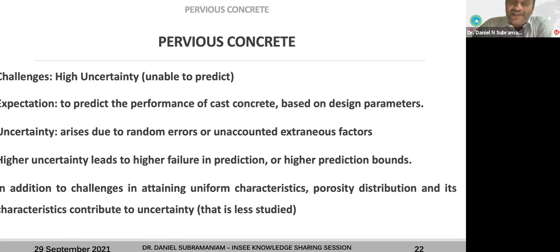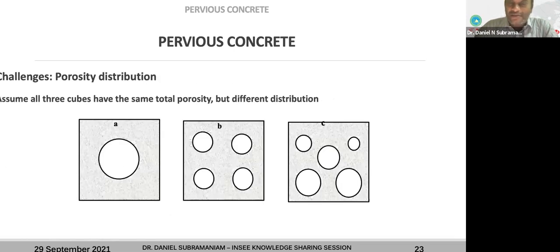So in addition to challenges in attaining uniform characteristics, porosity distribution and its characteristics contribute to uncertainty that is less studied. Most of the time, we will not be able to cast so many concrete samples. Concrete is already an uncertain material, because depending on the day that you cast, whether it's a rainy day or a dry day, whether the humidity is high or low, it's going to affect the concrete in some way, which is not going to be recorded and included in the models. So if you have more uncertainty with fewer samples, then the model predictions go way above the limit levels.